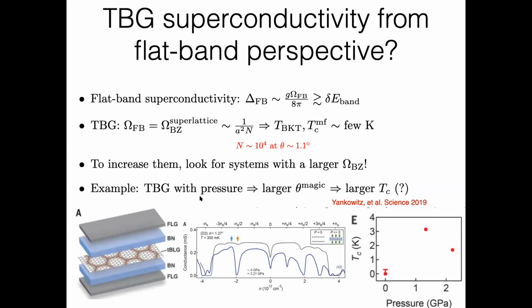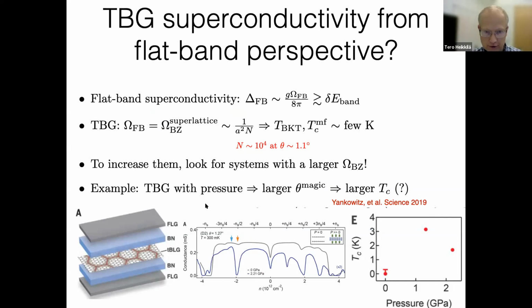So I'll try to make a conclusion of these studies. Flat band superconductivity requires that this flat band delta is large compared to the bandwidth. In the case of ABC graphene, this was definitely not the case. In the case of twisted bilayer graphene, it's actually a borderline case. The delta is of the order of the bandwidth, which means that you already need to consider the full band. Actually, you cannot do pure Fermi surface physics.